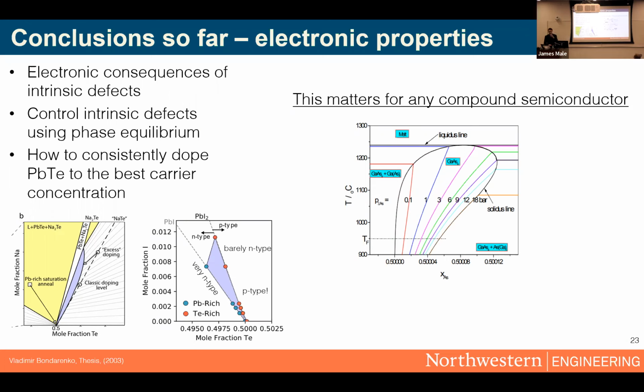Basically, this is a way to solve the inconsistencies in these samples because at a very simple level, we know N-type lead telluride should be lead-rich, P-type lead telluride should be tellurium-rich with an excess of sodium to consistently get the highest zT. These concepts might seem specialized to lead telluride, but in reality, any person studying a compound semiconductor should worry about them.